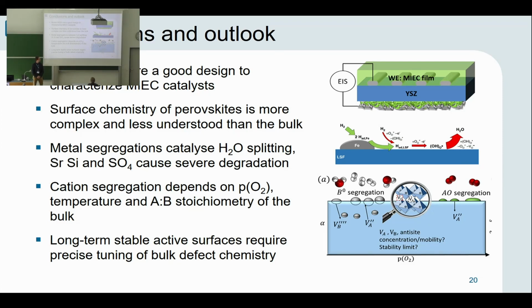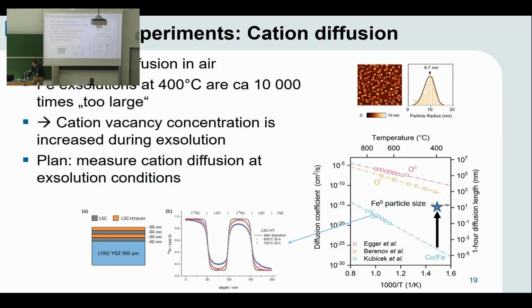So we investigated both epitaxial and polycrystalline films. And we see quite significant cation segregation on both films. On the polycrystalline films, which we deposit directly on the YSZ, it's usually more pronounced, but it's definitely very significant also on the single crystalline ones. For example, the films with the highest number density of particles shown here, which were exsolved at only 400 degrees, were epitaxial on perovskite substrates with different strain state.